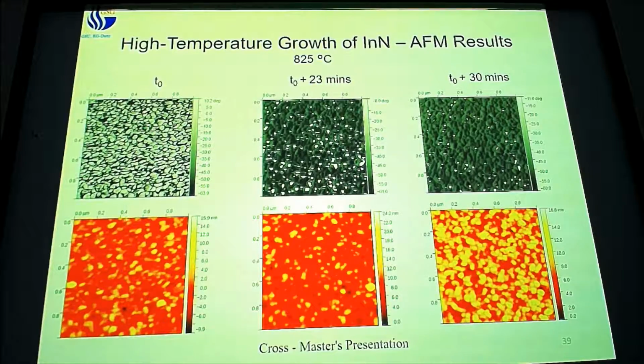And that's what's happening over here. On the bottom here, you see what the surface should look like. This is what it says it looks like. On the top here, you see a measure of the tip interaction. This is the phase difference between the driving force for that tip as well as the measuring time for that tip. So you can see over here, there are a lot of points on my material where that interaction is not happening rapidly. There is a change in the time. The time difference between it being told to move and it actually moving is large here. And the time increase here is from me grounding it.